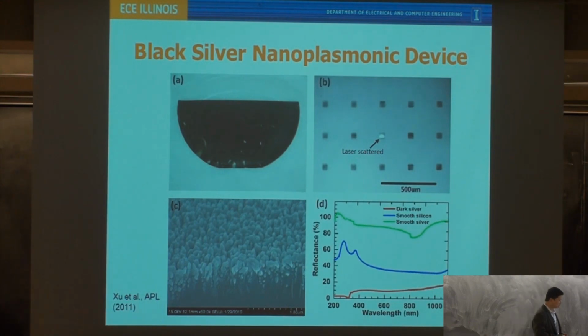Normally, you would expect that if you deposit a 100 nanometer silver film onto a substrate, it would be a very shiny mirror. But after you deposit it on this high aspect ratio nanocone structure, it still looks black. That means most of the light is either trapped in there, absorbed there, or transmitted through the actual substrate. So we do a reflection spectroscopy measurement to compare our black silver with a very smooth silver film. You can see a lot of light is being trapped inside the structures. It's not reflecting out.